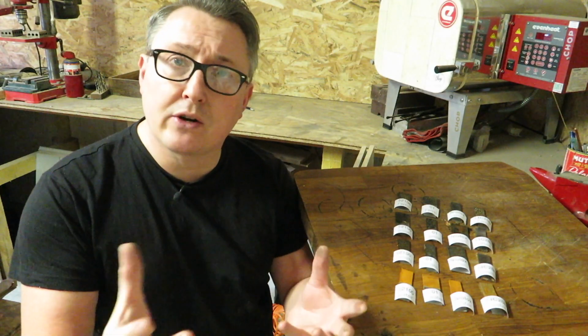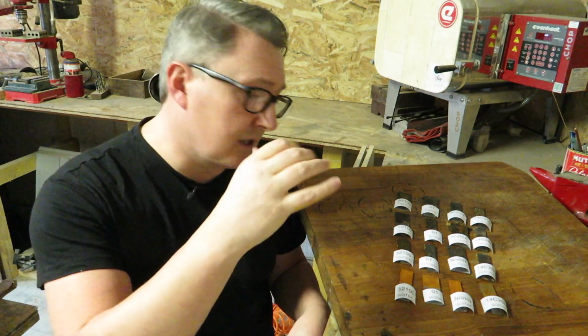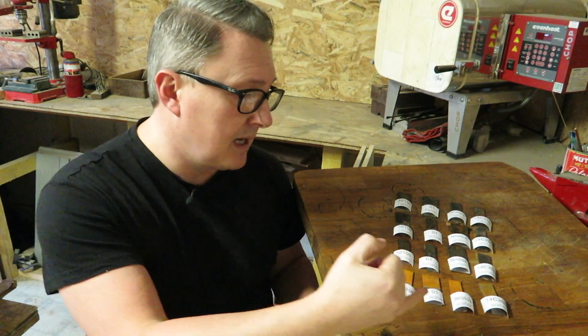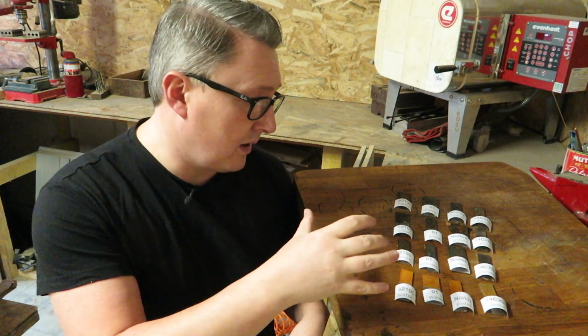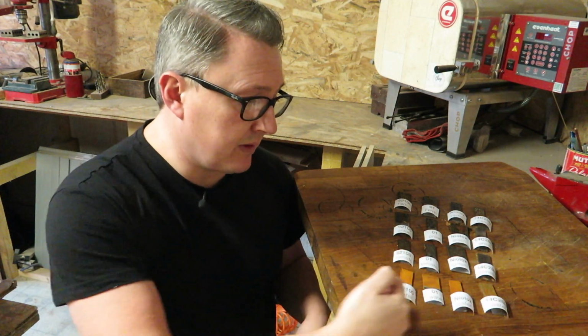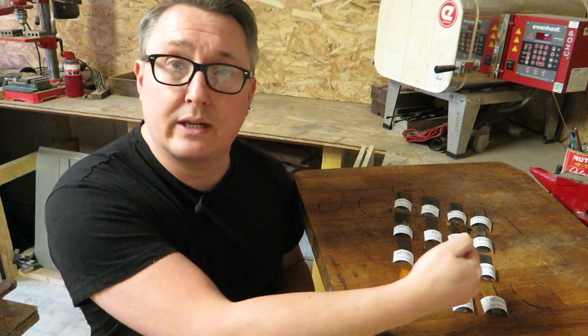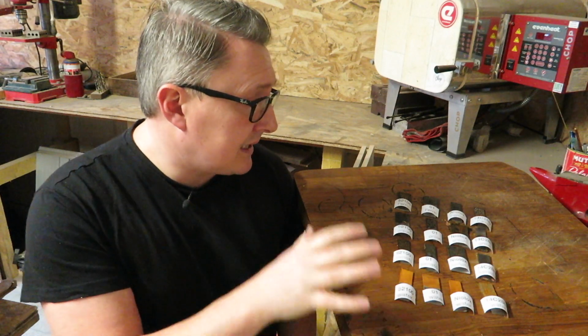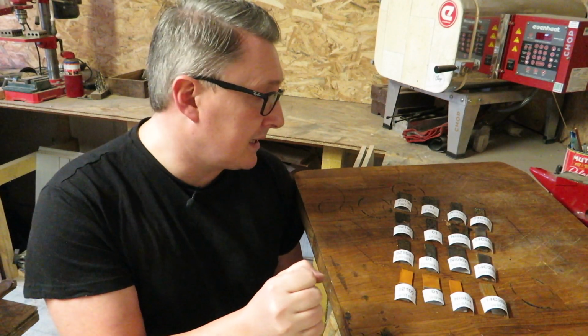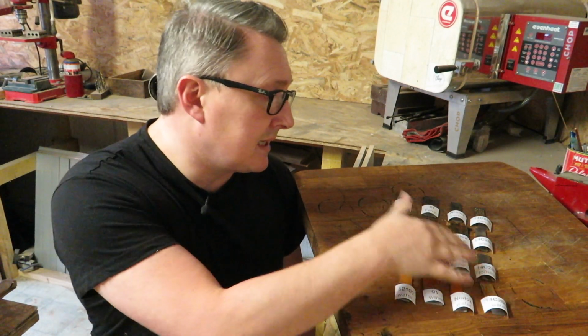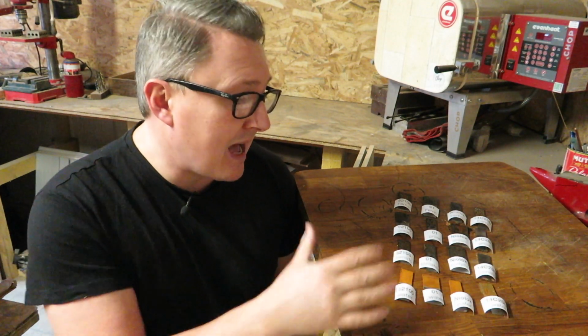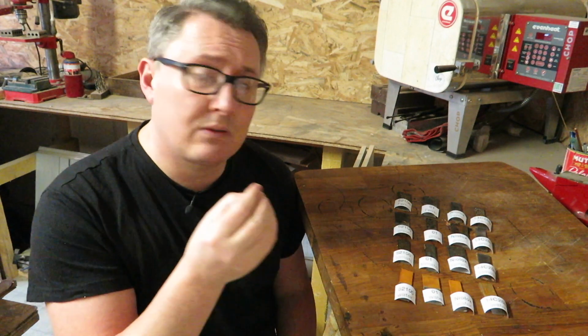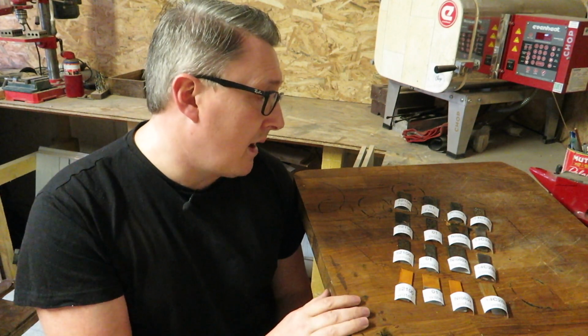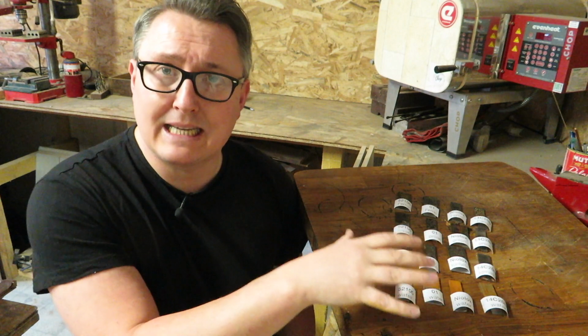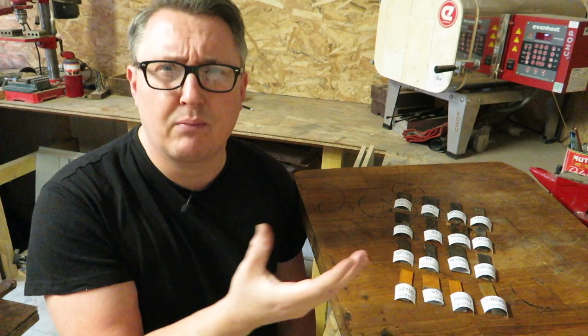So this test may be quite crude, but it's clear to see that the steels with the higher carbon content have clearly corroded a lot more than those without, particularly with regards to rust, which is the red oxidization we see here. The steels with the higher chromium content, such as the Niolox and the 14C28N, they've outperformed the higher carbon steels with regards to stain resistance, as we imagined they would do. But the ferric chloride really has eaten into all of the steels, I'd say probably quite equally.